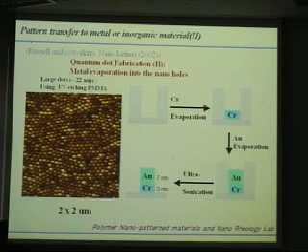First, they used a chromium evaporator, because they want to make gold nanoparticles, but gold cannot be in contact with silicon. So they first evaporate chrome, then they evaporate gold, so they can get a very nice quantum dot. That is a very interesting technique.